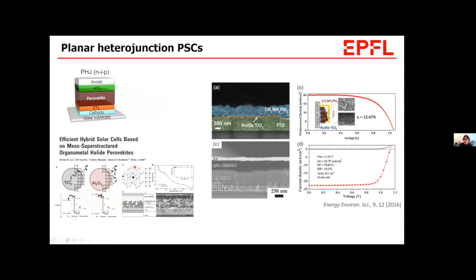This is what we looked at already. So inspired by this work, in which insulating aluminum oxide mesoporous scaffold was introduced, I said people questioned if mesoporous titanium dioxide is necessary. And there have been studies on it, without the mesoscopic structure. However, most studies at the beginning on this type of planar structure use the compact titanium oxide layer, which also needs to be processed at high temperature, like over 400 degrees C, which is still not compatible with flexible devices. So studies on low temperature process with compact layer have been required.